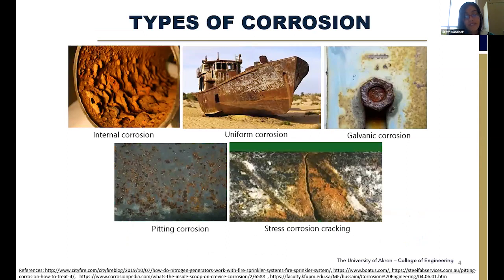We have different types of corrosion, and here I'm showing you only five. The corrosion can be uniform over the entire surface of the metal, could be with a pipeline internal or external. That will depend on the environment and the material that we use. It could be the interaction between two metals that can cause galvanic corrosion. The corrosion is not only uniform, it can be localized, like these little holes or pits that you see in the picture, like pitting corrosion. Or corrosion can happen when the electrochemical process is combined with a mechanical deformation, for example in pipelines, and that produces cracks, or stress corrosion cracking. So it has to be a combined interaction.